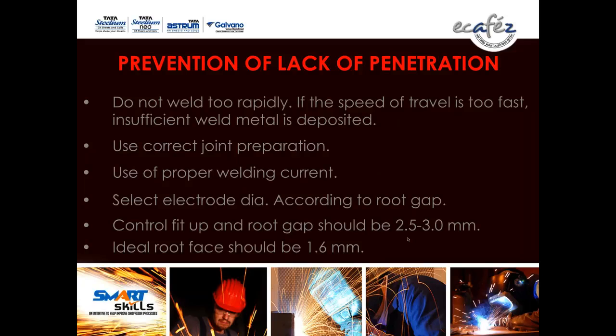Control fit-up and root gap, which should be 2.5 to 3 mm. Ideal root face, also called root land, should be 1.6 mm, but it can go up to 2 mm also. Sharp edge preparation should not be given to the welder, otherwise burn through or melt through will occur.